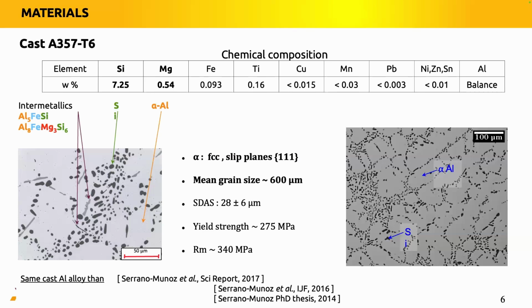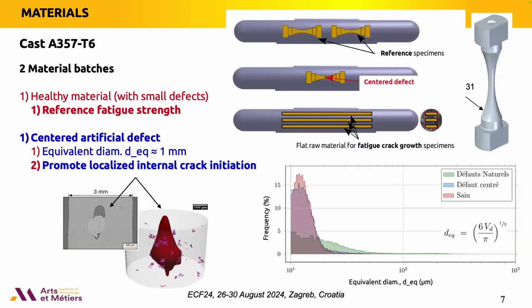Our material has a secondary dendrite arm spacing around 28 micrometers. This is an important parameter for the fatigue behavior. And we have the typical microstructure with an alpha aluminum matrix and silicon particles. These materials were cast in round bars in order to machine the specimens inside the bars. Two batches were prepared, in fact three, but today I'm presenting only two of them. The two batches of interest today are the reference batch, for the reference fatigue strength of the material with the smallest possible defects we can produce by casting. And the second batch is specimens with a single big defect in the center of the bar.